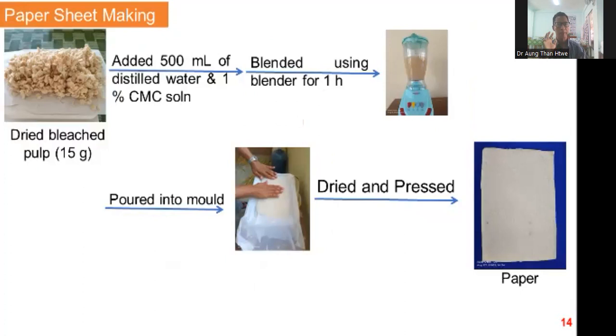Finally, paper making: the dried bleached pulp, 15 grams, and 500 ml of distilled water and 1% CMC solution were added and blended using a blender for 1 hour. And then we pour it into the mold, dry, and press it to obtain the paper sheet.